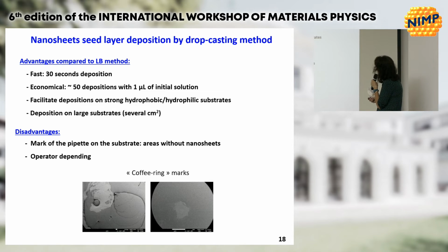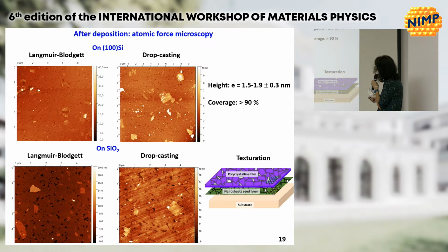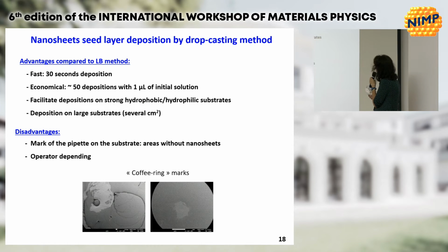Also, we can manage more easily the deposition on different kinds of substrates, which are hydrophobic or hydrophilic. It's easier than with the Langmuir-Blodgett method. And we can also use very large substrates. The main disadvantage is that we have some marks of the pipette in some locations on the substrate, as you can see here. We have this kind of coffee rings, and also it is very operator dependent.